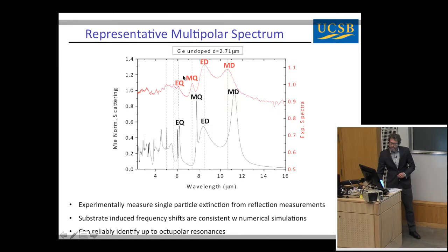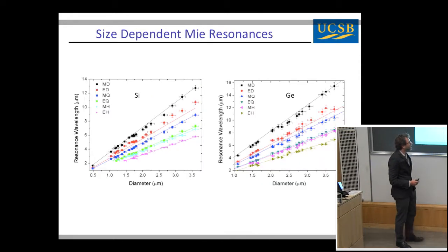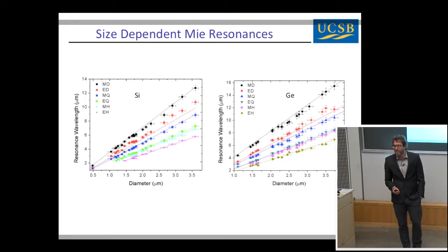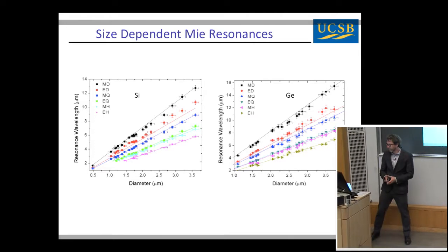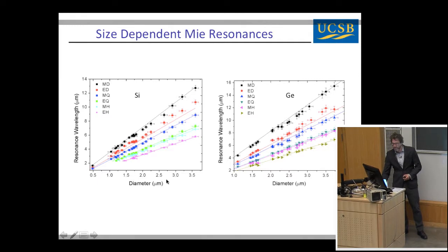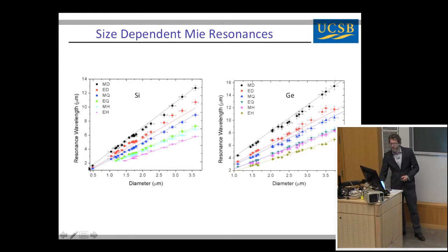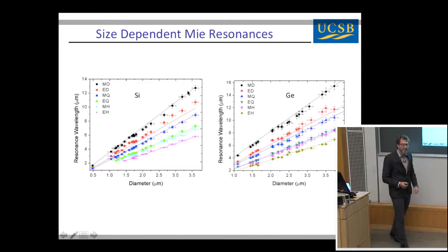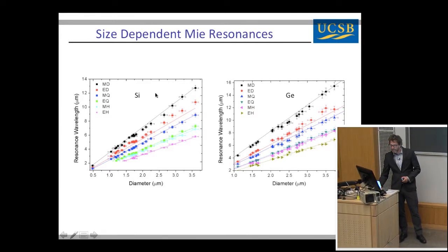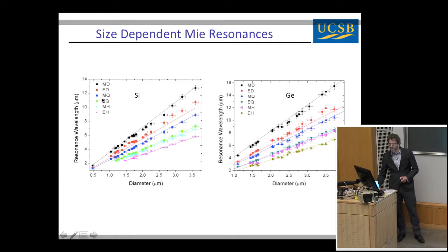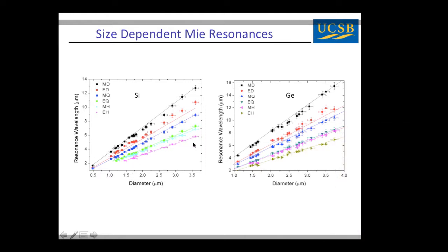And then over here, you might think it's not so clear that these little features in our experimental spectra correlate to our calculations. So one of the nice things about having all these different sizes is that Tomer can look at how these resonances evolve in wavelength as he looks at particles of different sizes. Okay? So these are different sizes. This is the resonance wavelength. And these are the first 6 multipole orders. Okay? And the solid lines are parameter-free lines that we get from Mie theory. And we can see that, indeed, we can observe these resonances spanning the IR from 2 to 15 microns, and that we can reliably catch even up to our hexapole order. Okay? So we can identify these Mie resonances even to these very high orders that haven't really been reliably seen before.